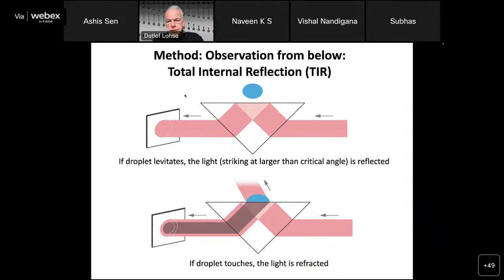So on the method, how do we look into this? Experimentally, I already showed you this high-speed color interferometry, but in addition, to look at even closer distances between the droplet and the substrate, we apply total internal reflection. So the principle is shown here. We have this prism, light comes in and light is reflected at this prism. And the way it's reflected, of course, depends on whether there is no droplet here or whether there is a droplet here. And with this trick, we can really probe the first, say, 10, 20 nanometers of this droplet, whether there is contact or not. So this is really the resolution which we can achieve.